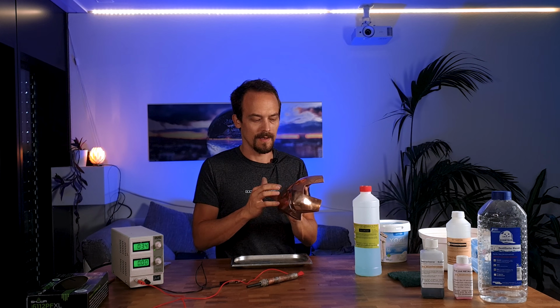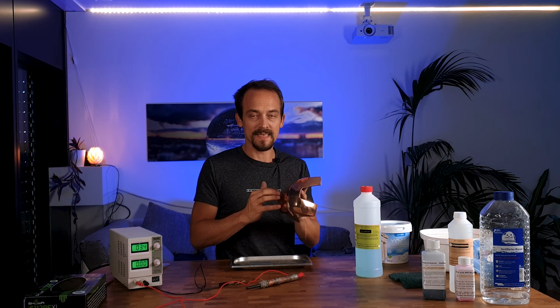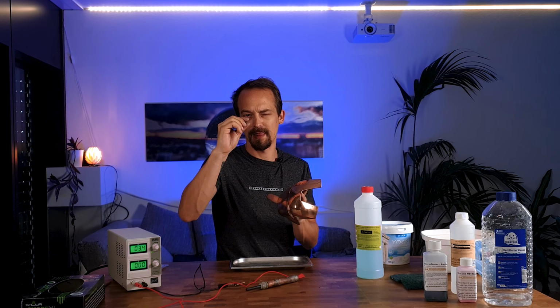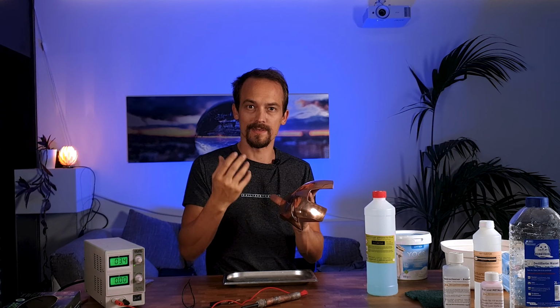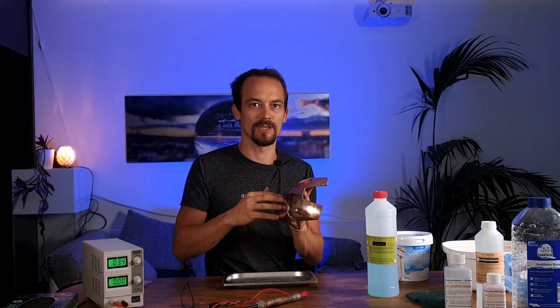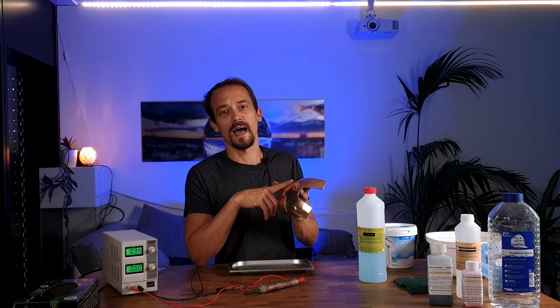I polished this mask to a partially mirrored surface, but as mentioned before, I want to have some battle damage. So I scuffed up the bottom and the sides a little bit and basically broke the copper layer. I have a little bump in the surface that looks very natural because it's actually damage. And then I copper plated again because I was down to the copper paint. So I copper plated thinly above that. Now I can get my nickel plating on there. But what it will do, it will always show the three-dimensional hole in your part, but it will be covered with gold.